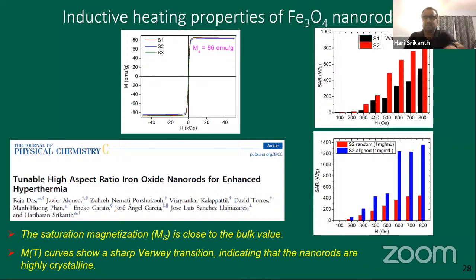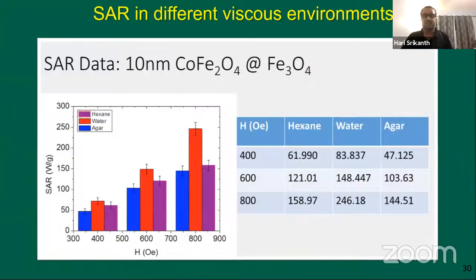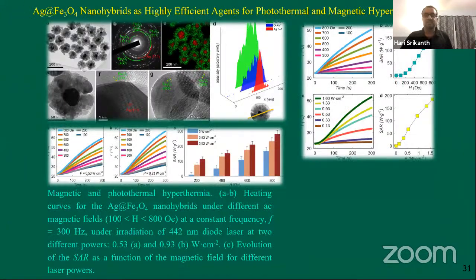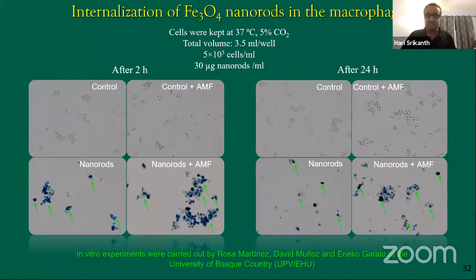So anyway, the nano rods gave us some of the best results in terms of the largest SAR. Again, the message is anisotropy is key. You can play with the anisotropy even with the known magnetic oxide and increase the SAR. So I'm going to skip a few slides, and point out that everything I told you today in this talk is only half the story, because I talked only about the material science part. We also need to worry about the biochemistry, because they have to be biocompatible, the surface has to be functionalized, and we have to look at the toxicity.